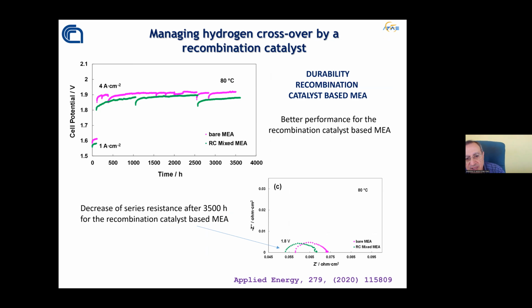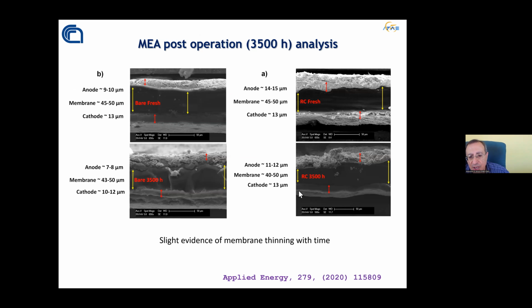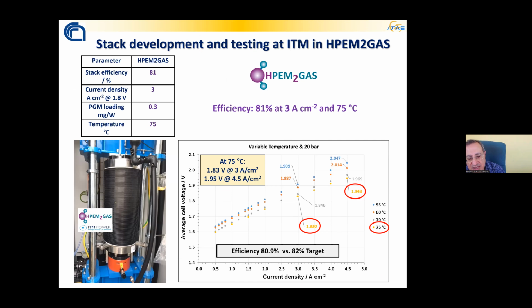You will be interested in understanding if using this recombination catalyst, we still have good durability. This slide shows tests of 3,500 hours, something like 4 months. In this test, of course, we have some startup-shutdown in between because we have some laboratory maintenance and so on. But what you can clearly see is that using the recombination catalyst, we also have better durability. We use a lot of post-operation analysis in our laboratory to understand membrane thinning, to understand changes in morphology, and to understand if degradation is related to these aspects.